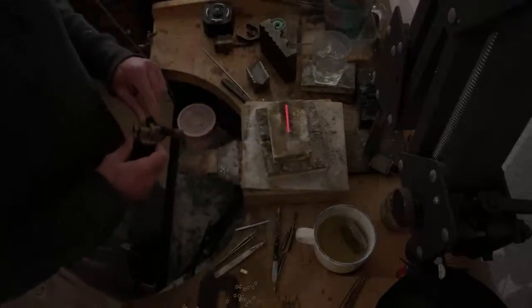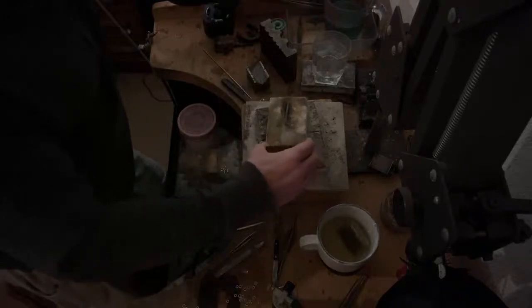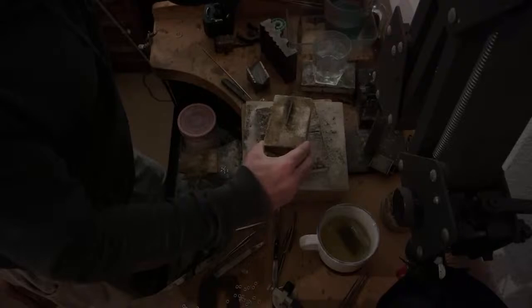Right, that should do us. It should be nice and soft. Now I need to quench in the water, but as I was saying earlier, I don't put it in when it's red hot. I let it cool down. It's still going to be a few hundred degrees, but I let it cool enough. Because like I say, I had issues with silver, not gold so much, taking on board water. And then when you rolled it out, you would get water coming out on the mill, which is obviously a problem. But also it would blister. Never found any information anywhere about that happening, but yeah, it happens. Right, next one.